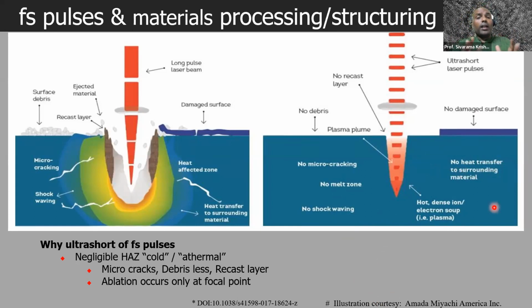The very important reason why these two are different is because femtosecond pulses predominantly generate a plasma, which is a soup of electrons and ions, to put it very crudely. Ionization is the primary mechanism with which these ultra short femtosecond or picosecond pulses interact and extrude materials. And this is something that is exclusive to femtosecond pulses, because the typical band gap of many of these materials exceeds the energy of a single near infrared or optical photon, and therefore you need to invoke nonlinear processes in order to ionize the material, which femtosecond pulses do very well.